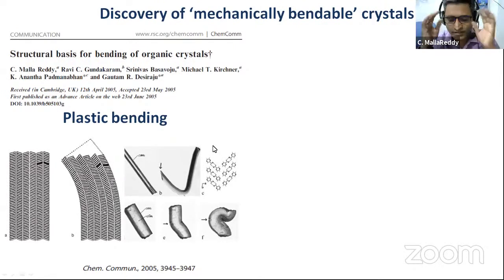The definition normally says that anything that gives you a diffraction pattern with X-ray can be broadly called a crystal. Whether you call it a single crystal or a polycrystal is still debatable. But from the crystal structure point of view, if you have a very broad beam, you overlap, because you're collecting data from different regions, and the orientation of the packing is different in different regions. So there would be overlap, but if you take a very small, very intense beam, you will now get a very good diffraction pattern.